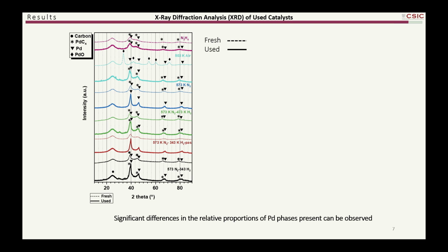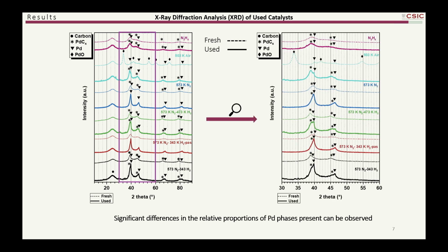We characterize the catalyst with X-ray diffraction analysis, and we characterize the fresh catalyst and the used catalyst, the catalyst before the reaction and post-reaction. And when we characterize the fresh catalyst, we observe significant difference in the relative proportion of the palladium phases that can be present in that catalyst: palladium carbide, metallic palladium, and palladium oxide. And when we characterize the used catalyst, we can observe several changes in these phases.